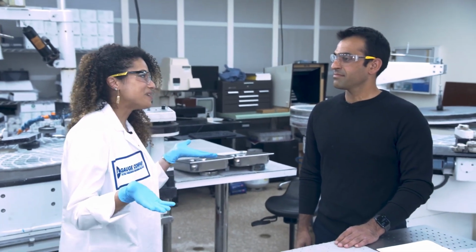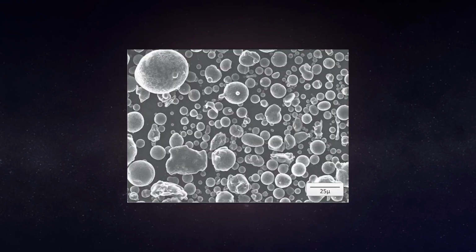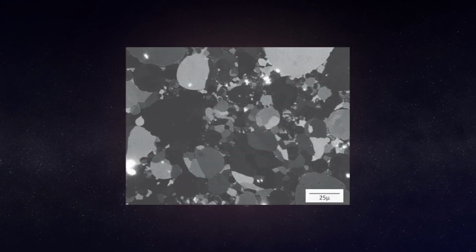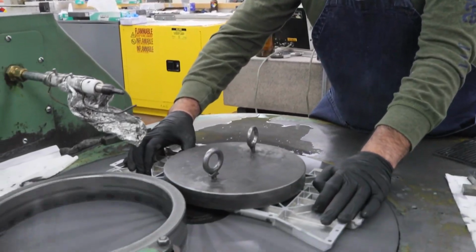Beryllium is obviously an incredible material, but everything does have its nuances. So, why isn't beryllium used more often? Machining beryllium requires extreme care. If you think about it, beryllium actually is a powder that is pressed together and requires very, very light cuts. Any small mistake, it would crack, and there'd probably be a piece that would chip off. And you've lost a part that could be worth anywhere between $1,800 to $2,000 a pound.